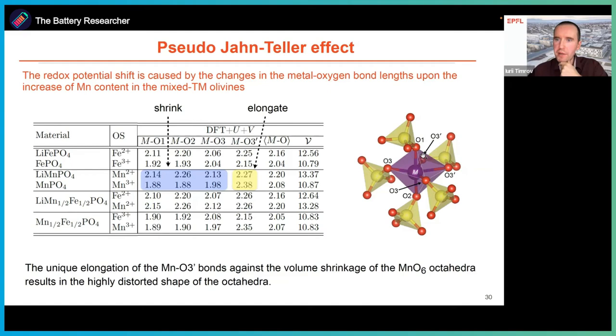So what is interesting is that when we delithiate the material, the total volume of the cell decreases, but also the volume of the octahedron decreases. So this can be seen also as a shrinkage of the bond lengths, all except those which are related to O3 prime oxygens. So it's very interesting because the volume decreases and all bond lengths decrease except two bond lengths which actually increase. And this is the so-called pseudo-Jahn-Teller effect.